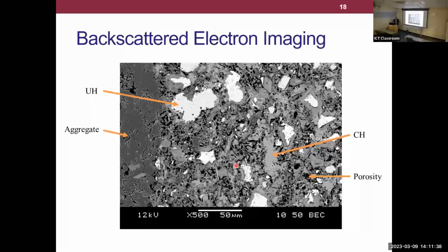So what we would see then is a polished flat surface of concrete. Here is our aggregate. Here we're using something known as backscatter electron imaging, just one of the imaging techniques we can use with an electron microscope. Everything shows up in grayscale. We can see our big aggregate surface here. Everything that shows up as white is unhydrated cement. Calcium hydroxide is this light gray. Everything black is porosity, filled with epoxy. And all the other grayscale is CSH and some of the other hydration products.